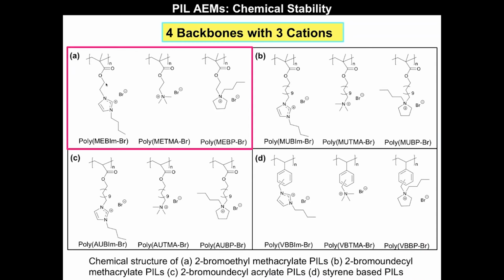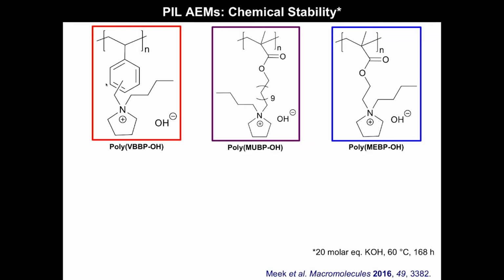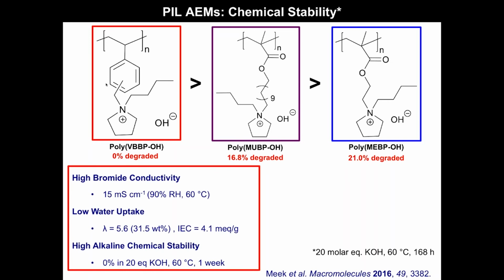We also looked at different cations on different backbones. So here's a sort of PMMA type with a long extender, acrylate with a long extender, and also styrene based. And here's just sort of a summary. So we found in all of these the pyrrolidinium was by far the best cation. And you can see on the styrene, we saw the best chemical stability. We actually saw no degradation under these conditions. So we found something pretty simple to make, not very exotic, with high conductivity, very reasonable water uptake at high ion exchange capacities, and, under these conditions, really high alkaline chemical stability. So now we're incorporating this into block copolymers, and our preliminary results show much better fuel cell performance. So that was very encouraging for us.